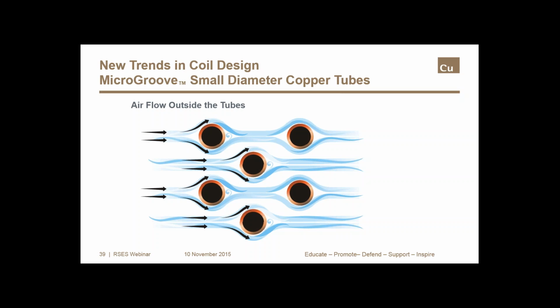Just as we saw with microgrooves inside of the tubes, outside, the tubes break up any boundary layers that the air tends to form as it flows through the coil. The more tubes we use, the more we break up the boundary layer on the air side, and the more heat transfer we'll get. But in many cases, more tubes also means a higher air side pressure drop. So there's a balance at some point where a coil uses an optimal amount of air to achieve the heat transfer that the system requires. Remember also that heat's being dissipated by the fins, and the fins have slots or louvers, again, to break up boundary layers and improve heat transfer.